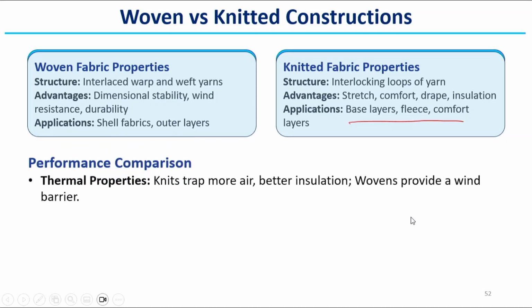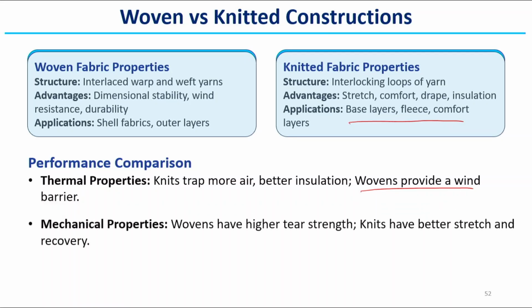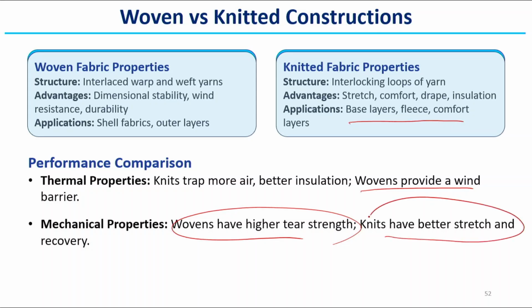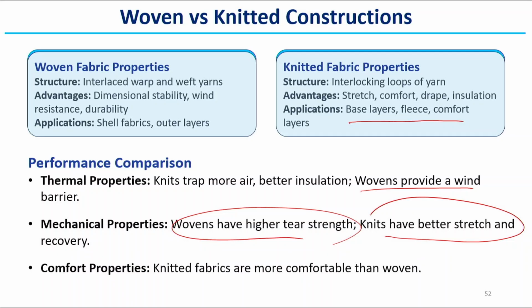Performance comparison, thermal properties: knitted fabric traps more air, so it gives better insulation, but woven fabric, due to its compact structure, has a high wind barrier. Mechanical properties: woven fabrics have higher tear strength and knits have better stretch and recovery. So, we can use woven fabric as the outer layer and knit as the inner layer. Knitted fabric is more comfortable than woven fabric because it conforms to our body movement, so it does not restrict the movement of our body parts.